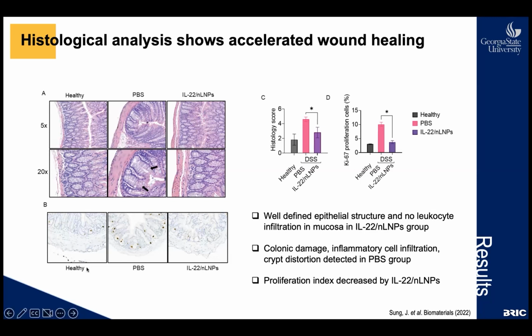Bottom left image is the proliferation staining, and it also shows the excessive proliferation in the PBS group compared to the healthy and the IL-22 lipid nanoparticle groups. And the graphs on the right side show the significant decrease in histologic score and the cell proliferation ratio in a quantitative manner.